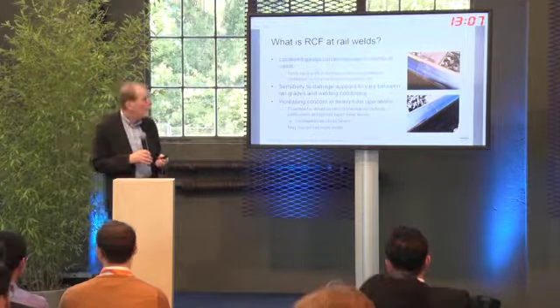The concern with them, first of all, is that if the cracks get too deep, of course, there's a risk of broken rails, potential impact on headwear limits, but also in terms of just getting the maximum performance out of the rails. So you find that it's actually the weld that can compromise the performance of the rail.